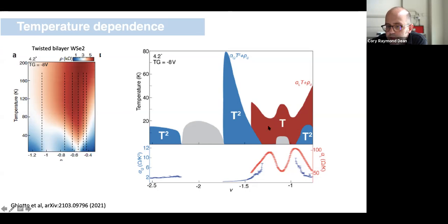So we say that, if we project all the way to low temperature, we're assuming that this point identifies the precise crossover where we transition from the insulating state and this kind of T-linear behavior to the T-squared behavior, the more conventional behavior. The other thing we note, which I don't think I have well articulated in this plot, is that where these two coefficients peak, where they diverge, and if we take that as the quantum critical point, coincides with the density at which we see the greatest temperature range over which T-linear behavior persists to the lowest temperature range that we have access to.